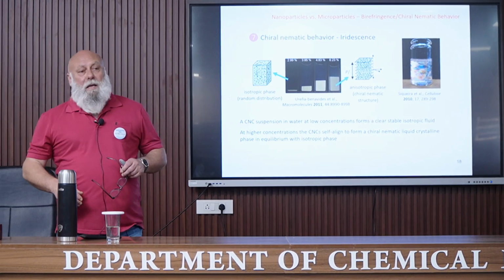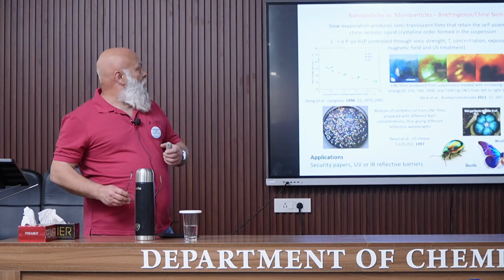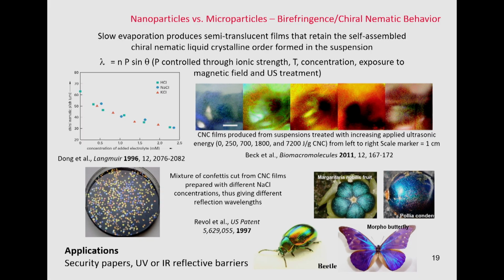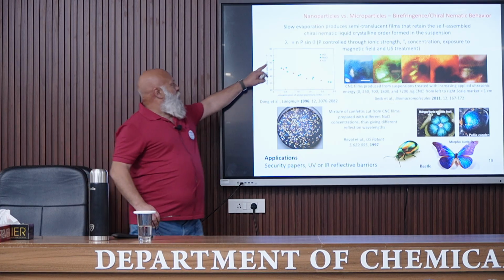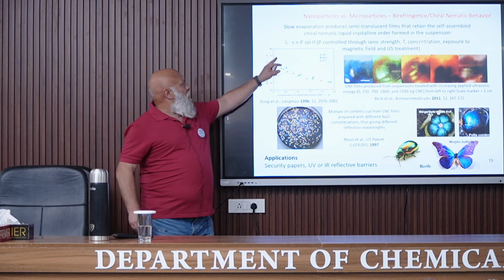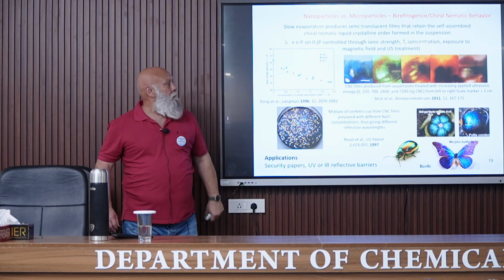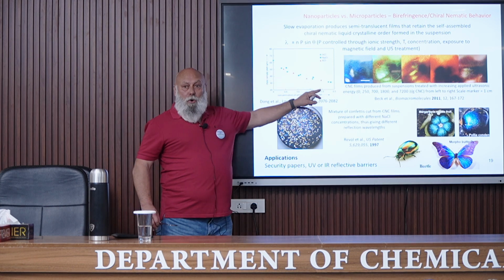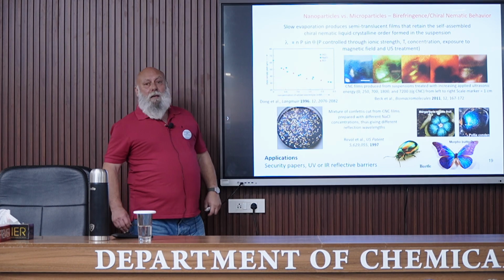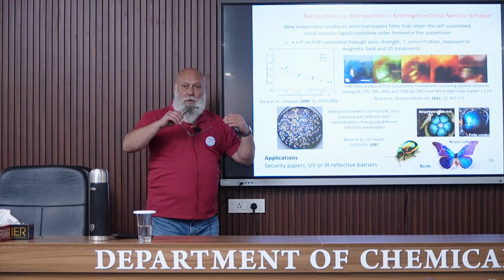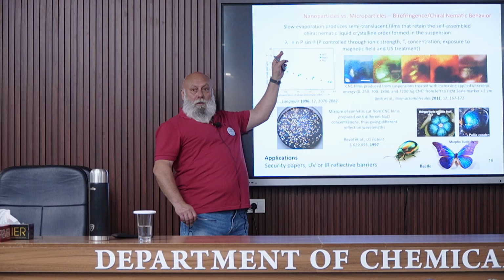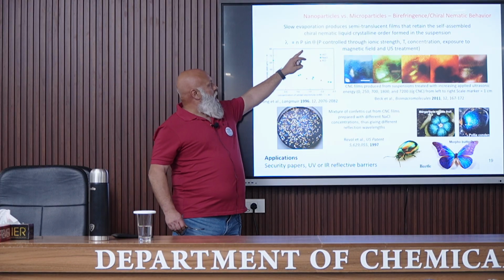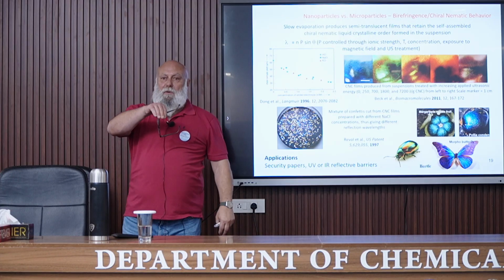And this organization can be preserved when evaporating water. But it's necessary to proceed to a slow evaporation, and we can obtain films, nanocellulose films, with some coloration. And this coloration refers to this wavelength here. You can see that it is linked to the pitch of the dispersion, and this pitch can be controlled, for example, by adding some electrolyte to the suspension. We can decrease the pitch of the dispersion, meaning that we can adjust or tailor the wavelength of the light, and it depends also on the angle of observation of the film.